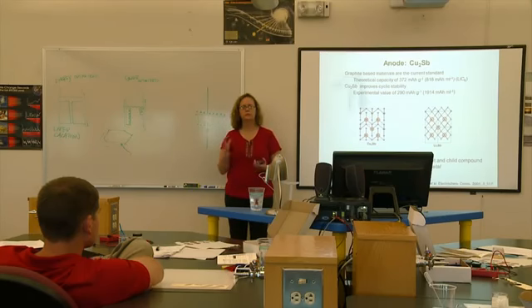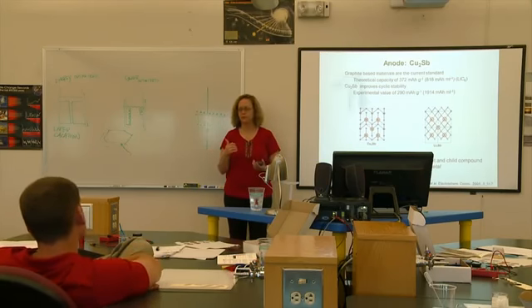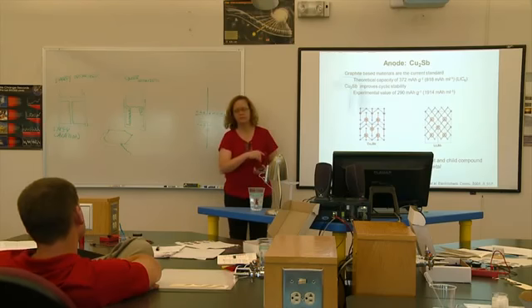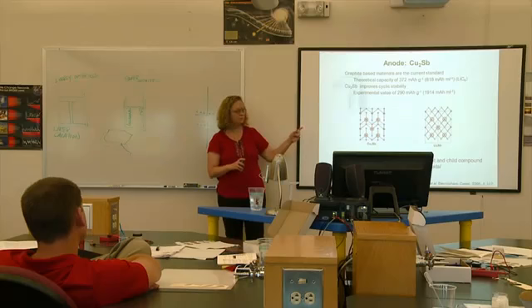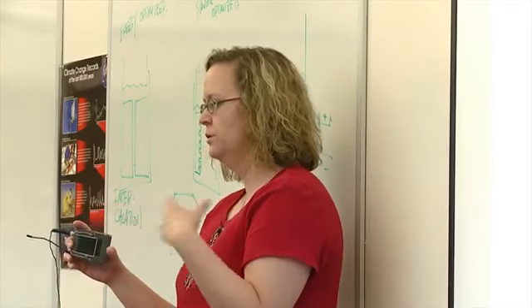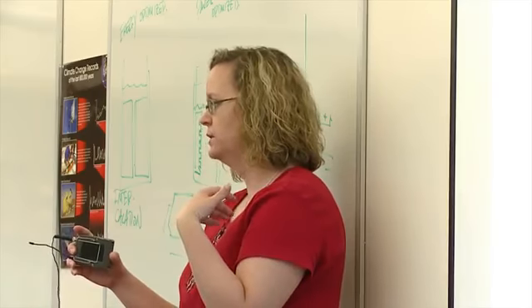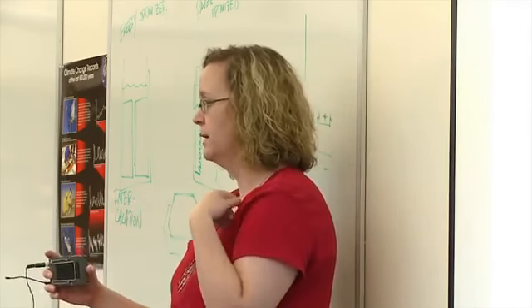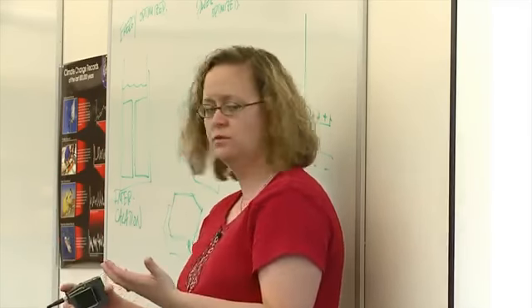Silicon has a 300% volume expansion when you put lithium into it. Copper antimonide is only about 75%, so it's a lot lower. And the reason it works is because the antimony atoms basically don't move. They make kind of a skeleton. The lithium goes in, the copper comes out, and then it's reversible. When you take the lithium out, the copper goes back in, and that's how you cycle it.